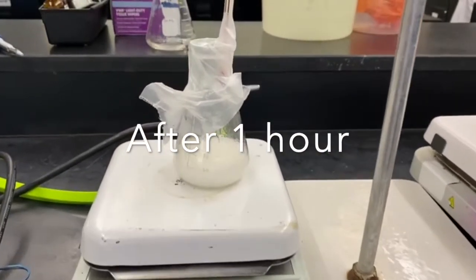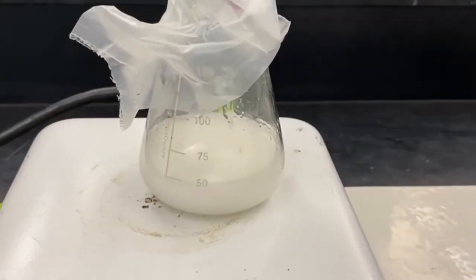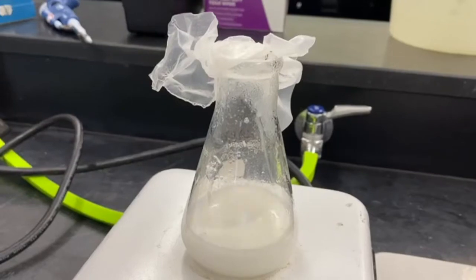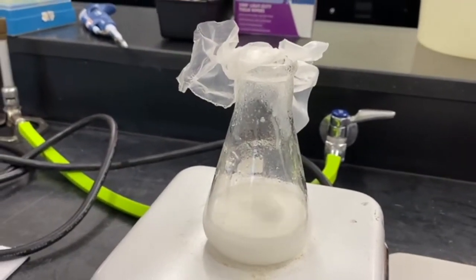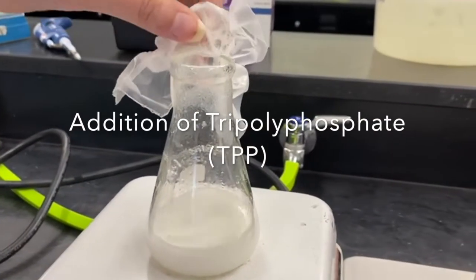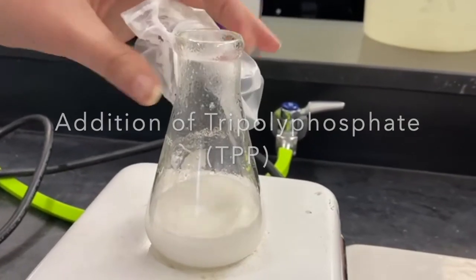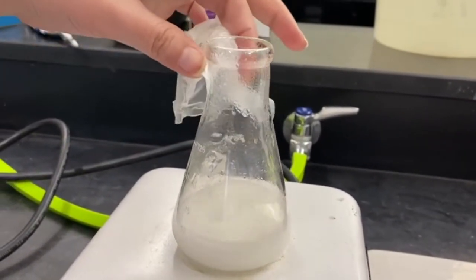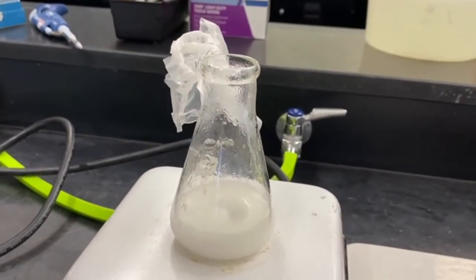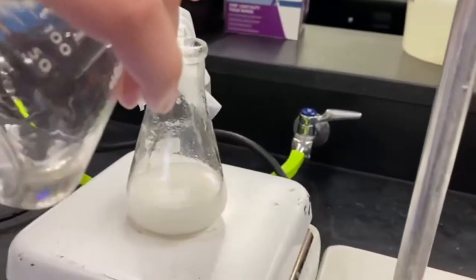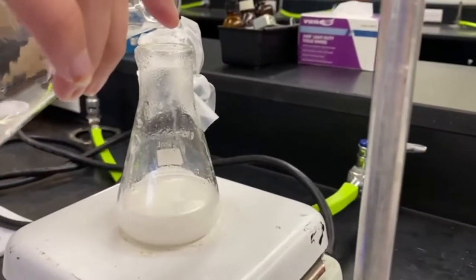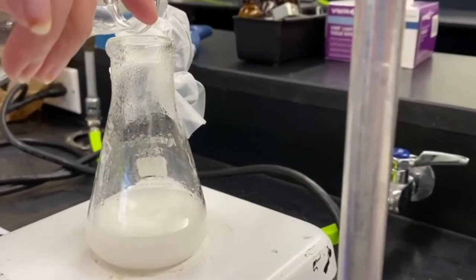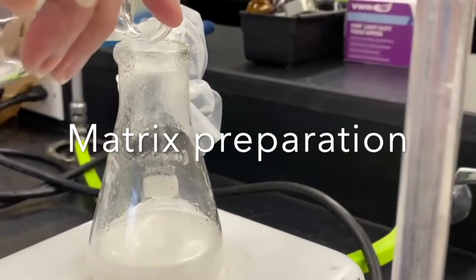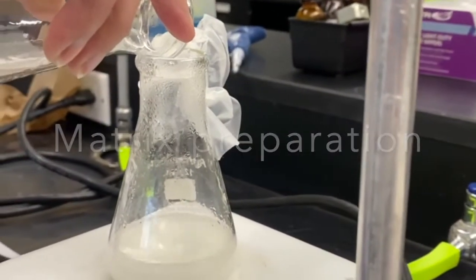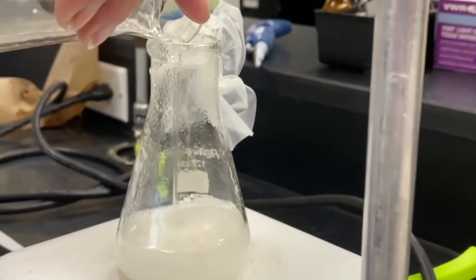So now we'll be adding 0.5% of sodium tripolyphosphate, TPP, which is a cross-linking agent, to the solution of Tween 80 with chitosan and thymol. We'll add it to this slowly to get a good matrix so that we can keep molecules in their place. The more we add this, the more we'll get the nice precipitate.